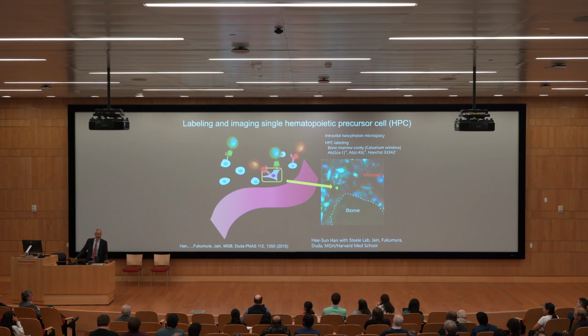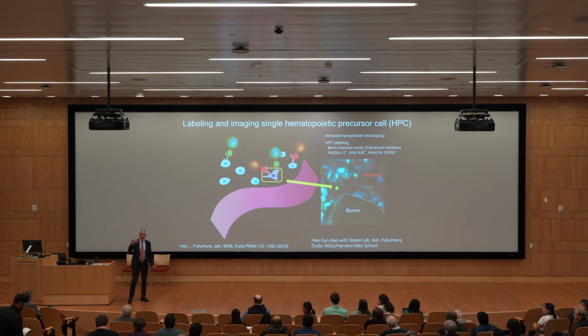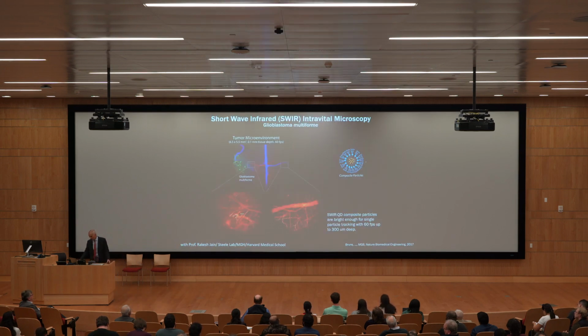And second, organic material really doesn't fluoresce in that wavelength range. It's completely dark. It likes to fluoresce in the visible. So if you have a visible emitter, you can have a lot of background fluorescence. It's hard to see things. But in the shortwave infrared, your emitter has a dark background, so you can see things much more clearly. Your signal is going to be much better. One of the experiments that we did was to look at blood flow in glioblastoma mouse models. So this is an experiment which is all done with quantum dots.